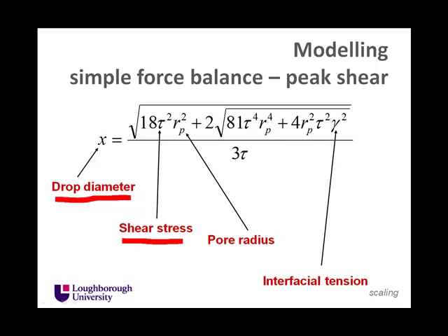The smaller the radius of the pore in the membrane, the smaller the drops will be. And the last parameter of great importance is the interfacial tension. The greater the interfacial tension, the larger the drop size. This model doesn't have injection rate in it.